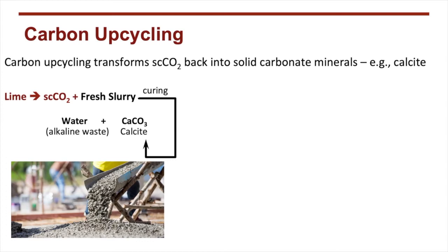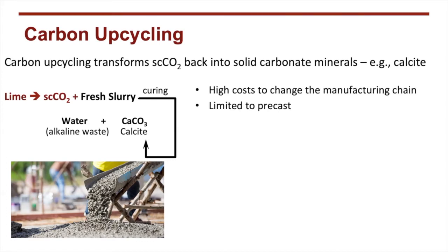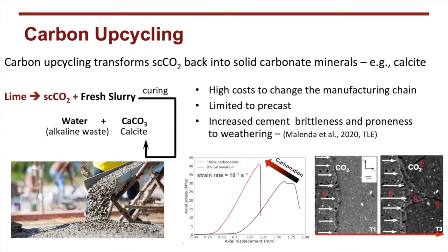But this approach has high cost because it requires changing the manufacturing chain. It's also limited to precast, but also the most important aspect to highlight here is that carbonation or carbon upcycling basically precipitates calcite. And calcite or any carbonate mineral is well known in the geosciences to be a mineral prone to dissolution and also a brittle mineral.